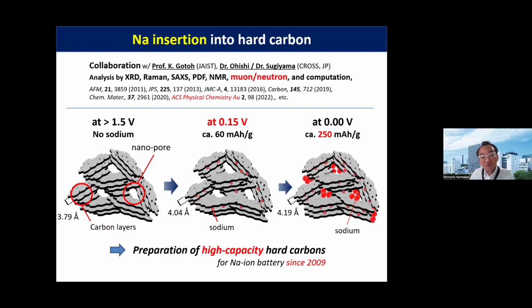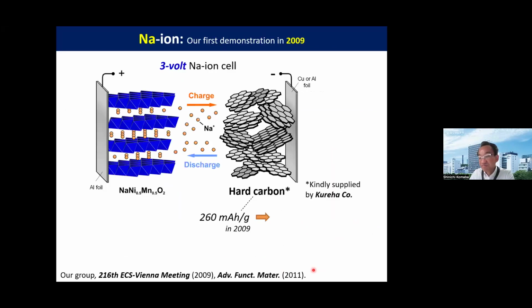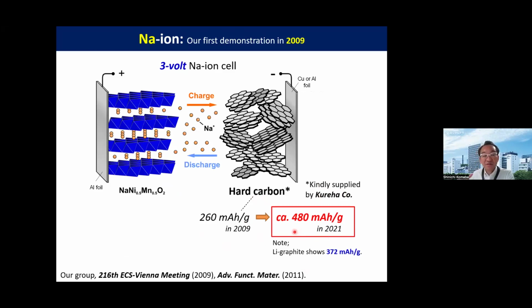And in the lower potential region, the sodium can move into the nanopores, so the sodium pore filling mechanism is also active for the electrochemical reaction. Based on such an understanding of the insertion mechanism, we can extend our study to synthesize higher capacity hard carbon since 2009. First, the hard carbon was kindly supplied by Kureha Co., and we achieved 260 milliampere hours per gram. But recently, we succeeded in much higher capacity of 480 milliampere hours per gram by changing the synthesis method to improve the hard carbon nanostructure. The paper is here.